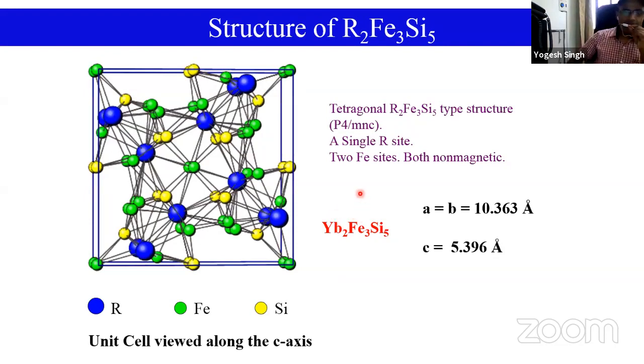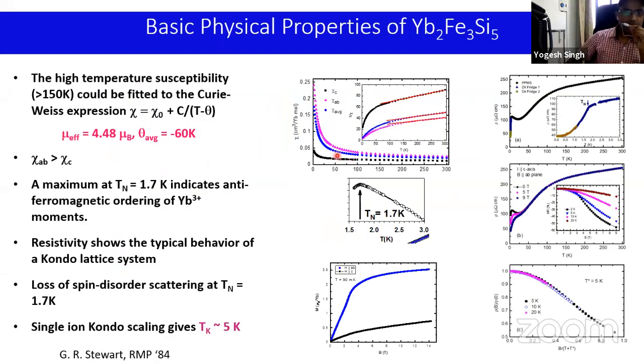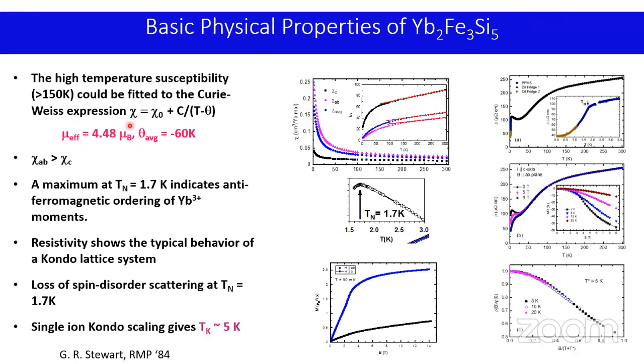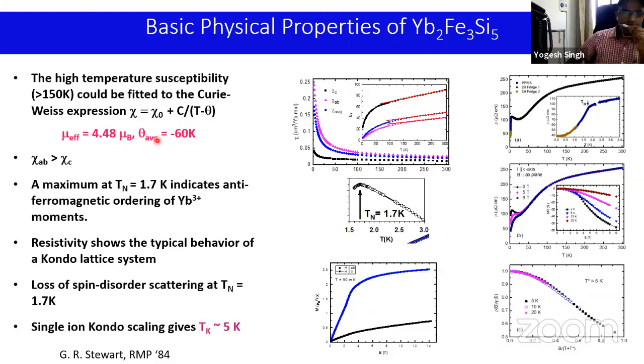Okay, so the crystal structure is tetragonal. There is only one ytterbium site and two iron sites, but both of them are non-magnetic, as has been confirmed by Mössbauer. So I start displaying the basic physical properties. Here is the susceptibility versus temperature, and you can see that the susceptibility with the field along the C-axis and the susceptibility with the field along the AB axis is highly anisotropic. This can also be seen in the magnetization at low temperatures, where you can see that the C-axis seems to be very hard, much harder to magnetize. So C-axis is the hard axis. The high temperature shows a Curie-Weiss behavior, and you recover the full moment here, and a Weiss temperature of -60 Kelvin.